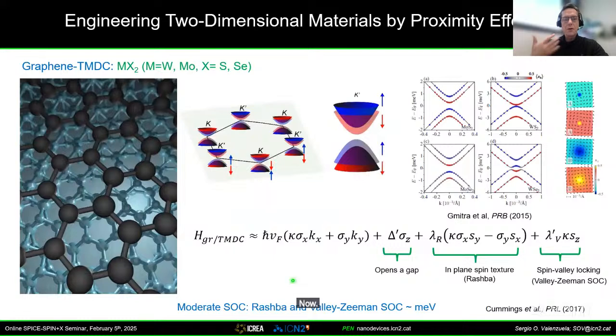Now, it was also known that if you combine this with graphene, and this was done in the group of Jaroslav Fabian 10 years ago, that you can imprint these properties in graphene. You can have this valley Zeeman splitting, which gives you this valley spin coupling, so a spin valley locking, and the splitting and the bands look very similar to those that you find in the transition metal dichalcogenide, with a scale that is much smaller, of course, because it's proximitized. Now you also have a Rashba spin orbit coupling that you don't have in the transition metal dichalcogenide, and this is because you put the graphene on top of or below a material that has large spin orbit coupling. You break the symmetry out of plane and so on.